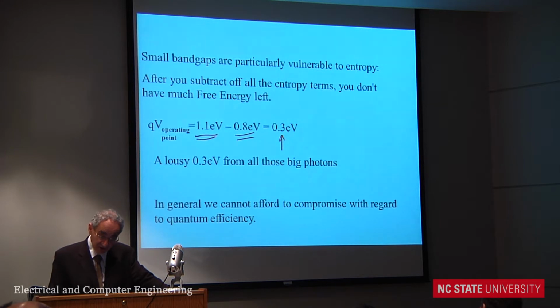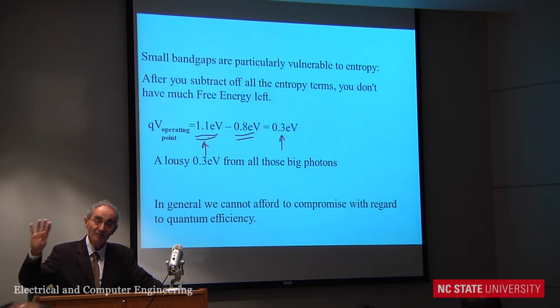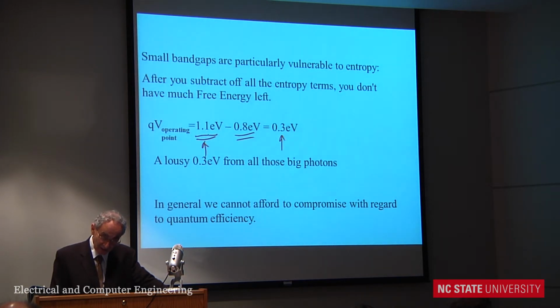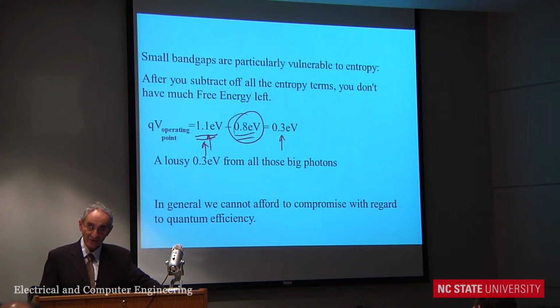Okay, and it also tells you to avoid narrow band gap solar cells. There are a lot of photons in the infrared, but they don't have much free energy. There's also a lot of entropy in the infrared. So don't vex yourself. Don't worry about capturing those infrared photons. There's energy, but there's not much free energy out there. Because whatever the band gap is, you subtract a fixed amount. So if you start with a small band gap, before you know it, you're getting nothing.